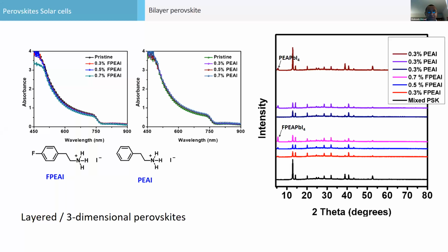And what we recently did is we take fluorinated and non-fluorinated molecules, because fluorine we know the surface tension is very high. They make the surface hydrophobic, or you say ultra hydrophobic, and we deposit a layer after annealing the 3D perovskite, and this is called bilayer perovskite. And the absorption onset was not changed. So there was no change we can see in absorption onset in both these materials, with fluorinated or unfluorinated.